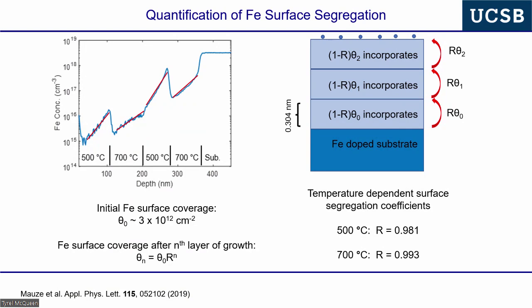Okay. We go to lower temperatures, and still most of the iron rides on the surface, but we get a little bit more incorporation. Okay. Now, for those of you that go into epitaxial growth, if you really learn the classic literature, you look at Pierre Petrov's literature from Bell Labs from the 70s, where he does actually impurity capturing superlattices. Okay, and they're called smoothing superlattices. In smoothing superlattices, you're doing high temperature, low temperature growth, or a refractory layer, non-refractory layer growth, and incorporating impurities, and you're actually purifying the surface by capturing the impurities.